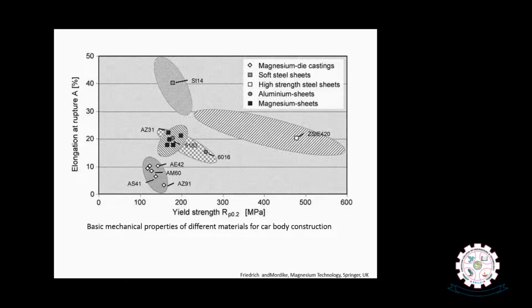Here you can see how magnesium die casting components and magnesium sheets, which are produced from rolled rod products, give us different mechanical properties. At the bottom, magnesium die casting components have lower mechanical properties, from an elongation point of view as well as a strength point of view. Whereas with magnesium sheets, the elongation almost doubled, and the strength of the magnesium sheets was also observed to be higher compared with the cast condition.